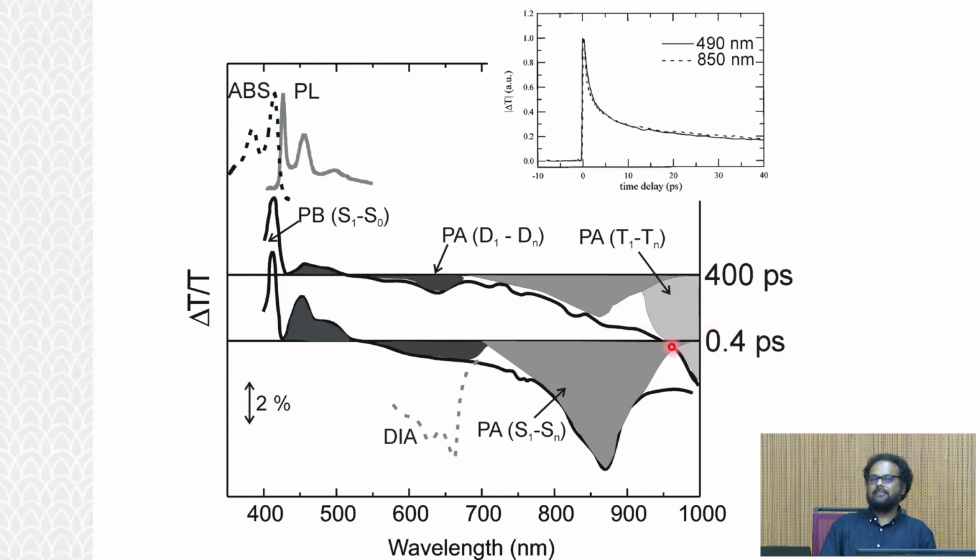In this particular system, at 400 femtoseconds delay, you have huge singlet states there, and also charge states, which means there's ultrafast dissociation of some fraction of singlets into charges. But if I look at 400 picoseconds, then I see another very large negative band here, which is associated with triplets, because intersystem crossing takes some time. So I can capture this kind of dynamics. Most of pump probe is basically analyzed this way. We don't need anything beyond it.